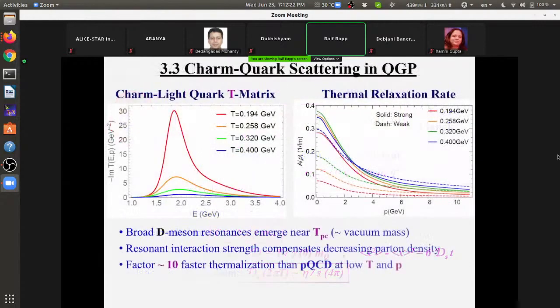Okay, so a quick look at the charm light quark T-matrix. It's not so different from the bottom side - these D mesons melt quicker. But as you go close to TC, there will be these strong D meson resonances, and those are really essential drivers, accelerating the thermalization rate roughly by a factor of 10 compared to perturbative interactions.